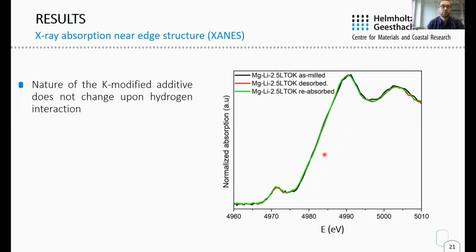One of the questions we may also ask is whether there is any change in the nature of the additive during hydrogen absorption and desorption reactions. And the answer is no, as we see in this graph. Titanium has the same oxidation state in the as-milled, desorbed and reabsorbed samples. The results tell us that the additive may act as a catalyst rather than changing the reaction pathway.